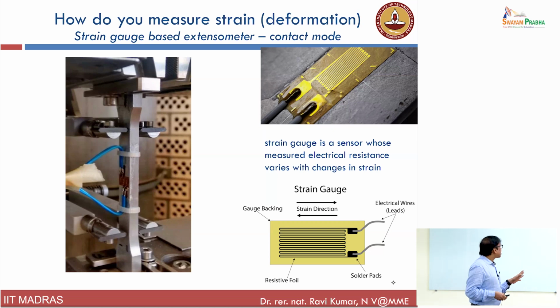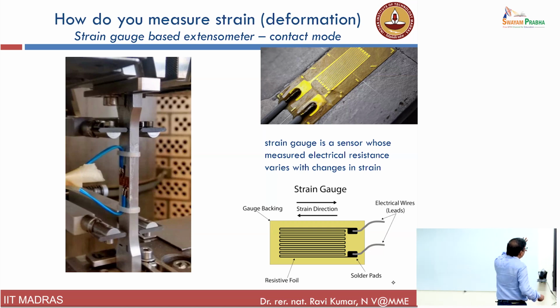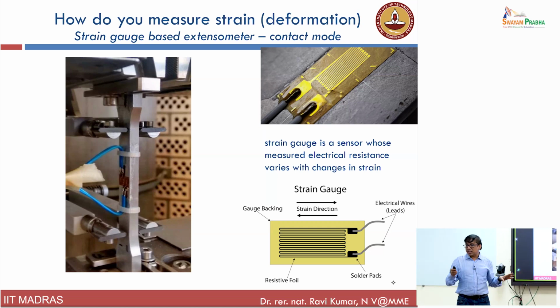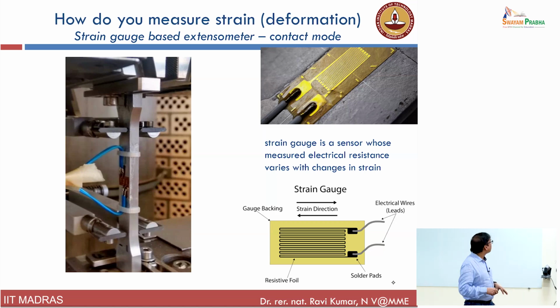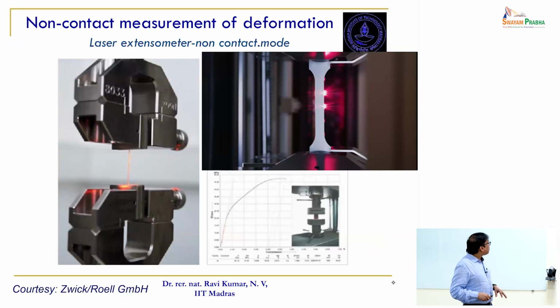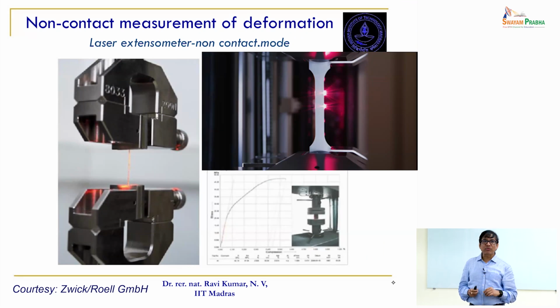And for that, of course, you have strain gauges. People use contact mode strain gauges. And you fix the strain gauges and then measure. Again, easy to do for metallic materials and not so easy to do for ceramic samples. But in modern times, people use laser extensometer. So you can use a laser extensometer to really see the change in length because of the application of tensile load. That's a non-contact mode. And typically also very much relevant, for example, if you have wires.